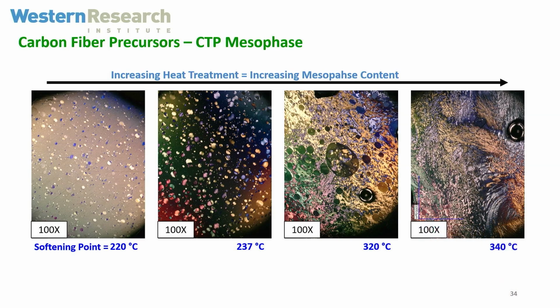To make carbon fiber, one of the traditional ways is to take coal tar pitch and heat treat it. What you see here, these little bright colored spheres, is a liquid crystalline phase that gets made in that heat treatment. You keep heating it and you make more and more of those spheres. Eventually you make so many, it's like an emulsion, it goes into a phase inversion and becomes a continuous phase. This liquid crystalline phase is what you need to make good carbon fiber with high strength and high stiffness.